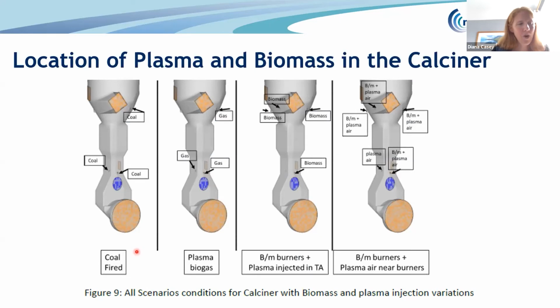So this diagram on the left here is the coal-fired case. So this is the sort of reference plant at the baseline, 100% coal. In scenario 1, which is this one here, the plasma burners are used kind of external to the calciner, almost to produce gas by gasifying the biomass, which is then introduced at about 1,000 degrees C. So you can see it just says gas, I think, on each of these inlets.